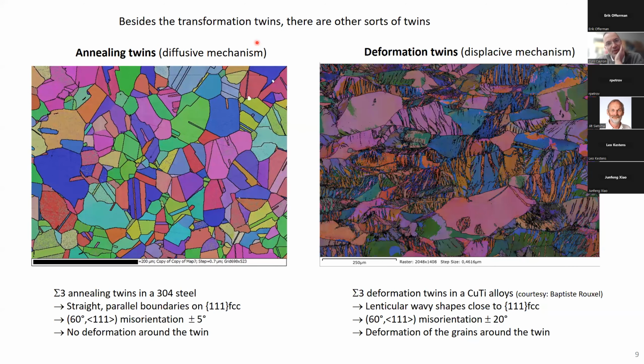Okay, so I tried to introduce what transformation twins are. Actually, they are variants created by martensitic transformations, but there are other sorts of twins. The annealing twins are formed when you deform a low stacking fault FCC material and then you heat the material. You will create recrystallization and grain growth inside the material, and during the grain growth, some accident on the 111 plane of this FCC material can appear. So it grows like that, and then suddenly it changes the orientation into a new orientation, and it can do this alternatively on different 111 planes. And so you create these annealing twins. They are straight, they are parallel to the 111 direction of your FCC face centered cubic material.